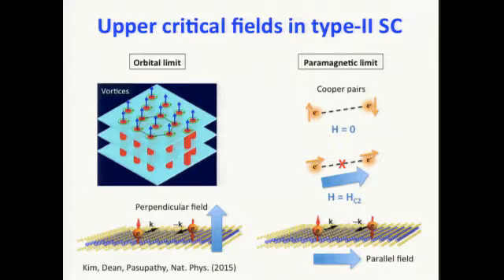Cooper pairs are formed by electrons with opposite spins, spin up, spin down. So what it means is that in the singlet state, if you apply a magnetic field, the Cooper pairs are just indifferent to the external magnetic field until the field becomes so big that the pairs are flipped by the field. And this is the pair breaking field. And then the superconductor is quenched in this limit.